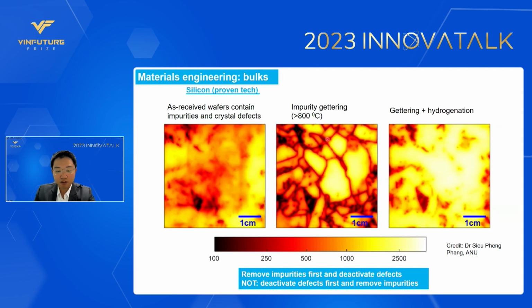We have a method called impurity gettering by thermal diffusion process. After a thermal diffusion step at very high temperature, most of the impurities can be removed out of the wafer, but the crystal defects are still there. Then if we continue with a hydrogenation process, we can basically deactivate the crystal defects.